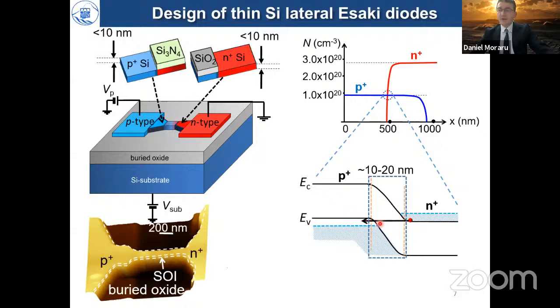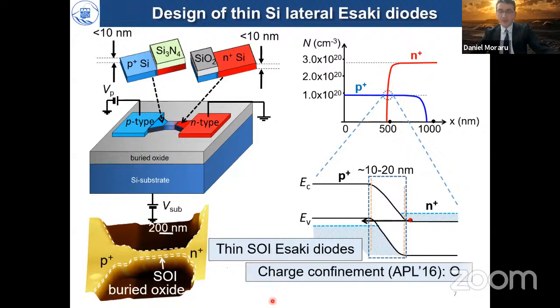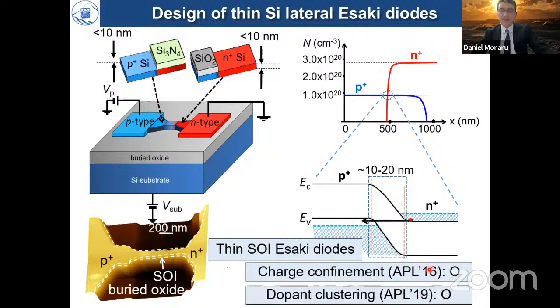So we are actually looking at thin SOI Esaki diodes, and we'll report two main results. One is that because of charge confinement in such small scales, we get deepening of the energy states of dopants, and we reported this effect in Applied Physics Letters in 2016. And the second effect is because, again, of low dimensionality, we obtain dopant clustering, and it has a significant effect in the transport characteristics. And this was reported in Applied Physics Letters in 2019.